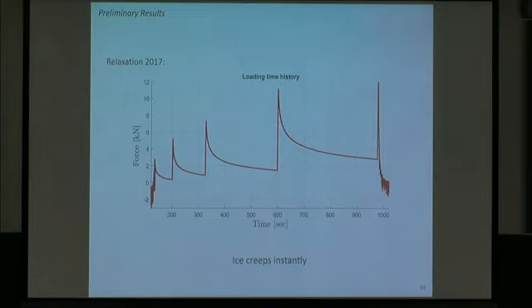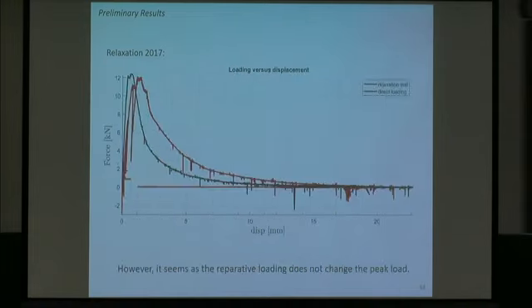Okay, in 2017 we did the same test, but with a faster speed. This was done with 50 times faster speed. We load it up and then wait until it goes down. We load it up, wait until it goes down, and several cycles until eventually we load it up until it fractures. And then the question again is whether or not this peak force would be the same as direct loading. Again, it's almost the same. So the dark curve is direct loading until it fractures, and the red curve is what I just showed you, with this cyclic relaxation, and the peak force is almost the same.